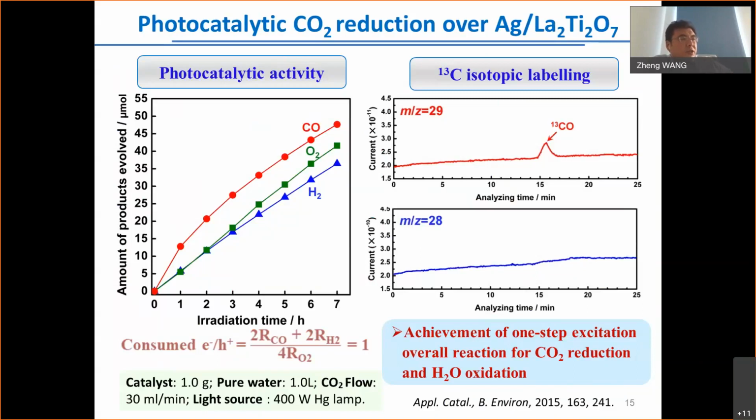Moreover, 13C-labeled carbon dioxide was used in an isotopic labeling experiment, which confirmed that the carbon monoxide product originated from the introduced carbon dioxide gas, not from organic pollutants.